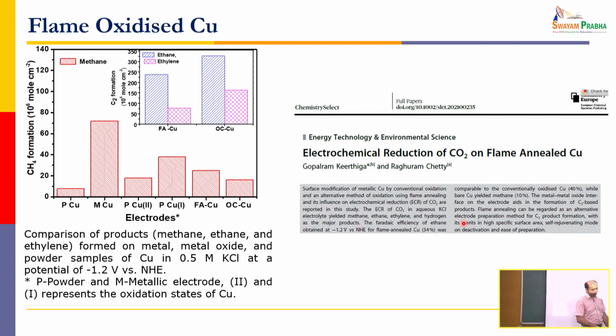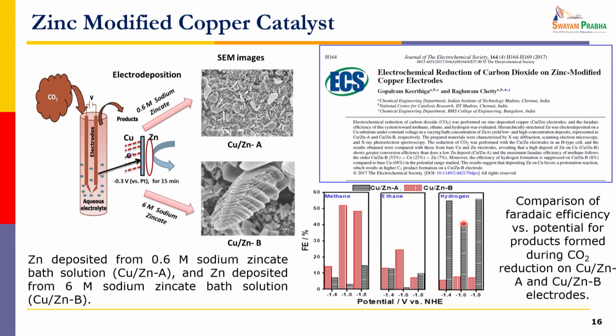So these are some demonstrations to show that we are able to convert carbon dioxide into some fuels. And as I said, hydrogen evolution is one of the major problems when you pass carbon dioxide and apply a potential. In addition to carbon dioxide reduction, water reduction and hydrogen evolution will happen. So what we have done is, we have deposited some zinc. Zinc is one material where hydrogen can be suppressed. So we deposited different concentrations of zinc. This is a low concentration, 0.6 molar was used for deposition. We used a high concentration, 6 molar, and we get different structures based on how you deposit on the copper.